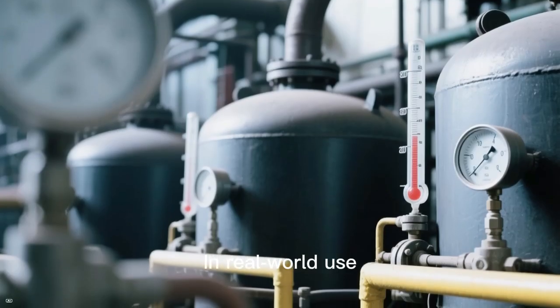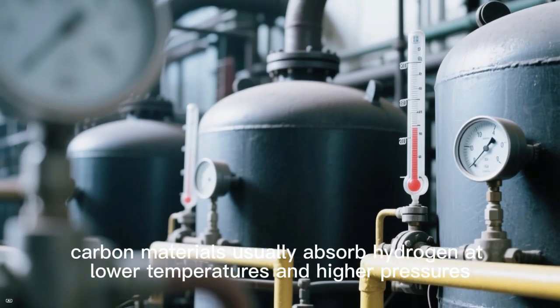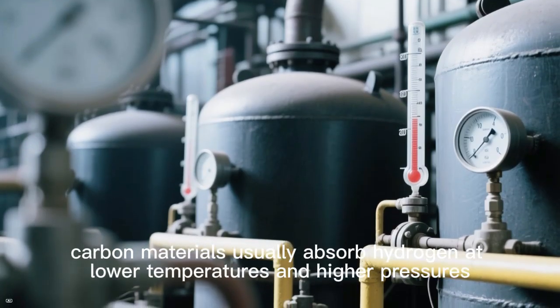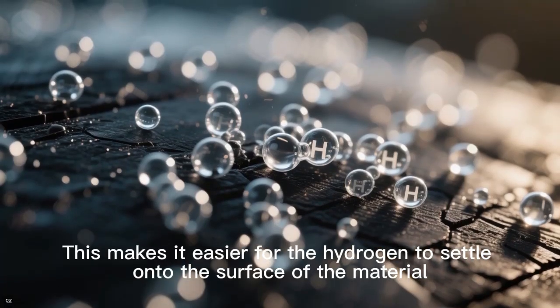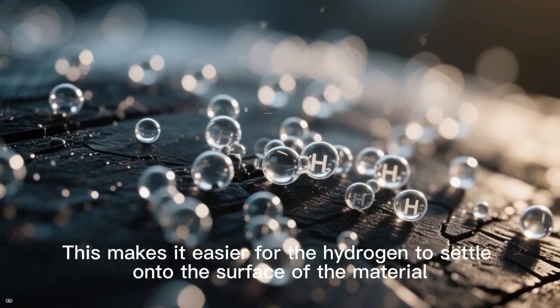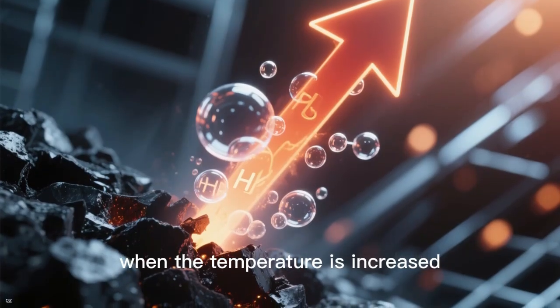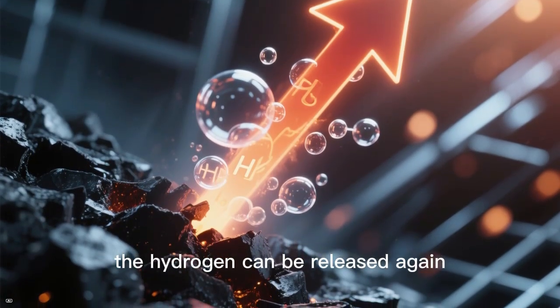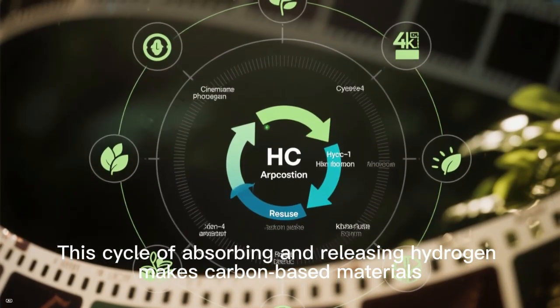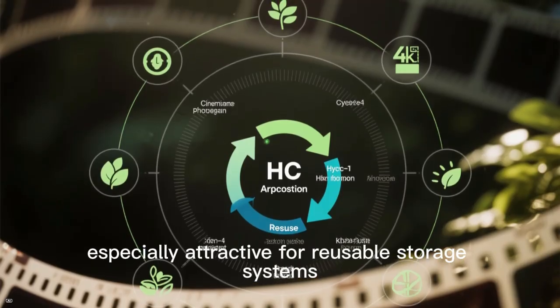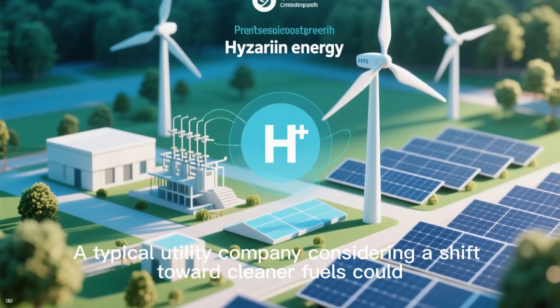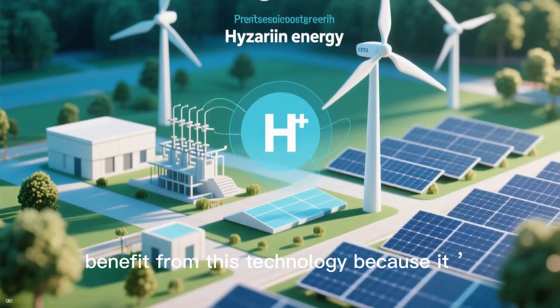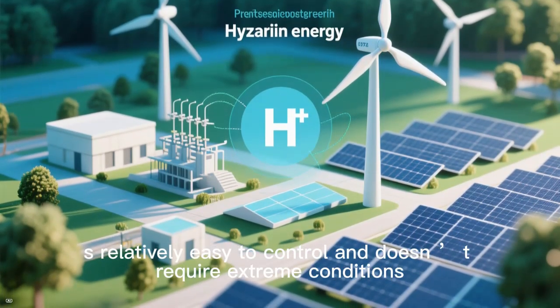In real-world use, carbon materials usually absorb hydrogen at lower temperatures and higher pressures. This makes it easier for the hydrogen to settle onto the surface of the material. Later, when the temperature is increased, the hydrogen can be released again. This cycle of absorbing and releasing hydrogen makes carbon-based materials especially attractive for reusable storage systems. A typical utility company considering a shift toward cleaner fuels could benefit from this technology because it is relatively easy to control and doesn't require extreme conditions.